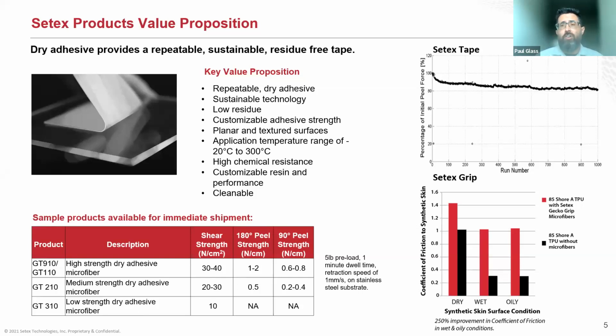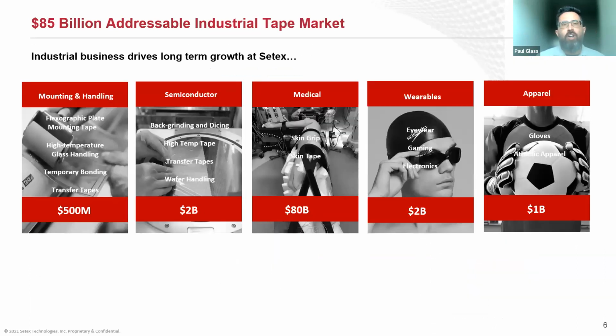Also, because we're using fully cured materials to form our pressure sensitive adhesives and not lightly cross-linked tacky tapes, we can produce our materials from elastomers or polymers that have good temperature resistance. So we can provide tapes that work over a much wider temperature range than most conventional adhesives, as well as have good chemical stability. Our grip materials, showing some data here on the bottom right, maintain really excellent coefficient of friction in dry conditions, as well as wet and oily conditions. You can see the data here in red is our Setex materials contrasted with a smooth elastomer made from the same resin in black, which has good adhesion and good grip in dry conditions, but loses performance in wet and oily conditions. It's a huge addressable market for our materials.